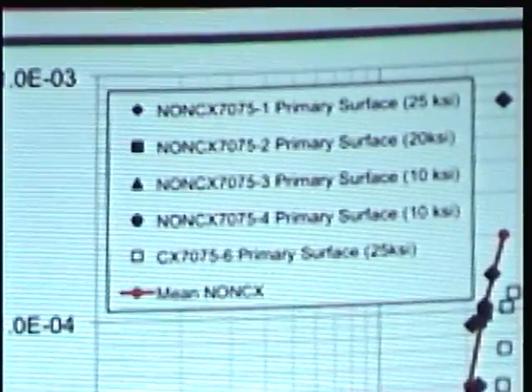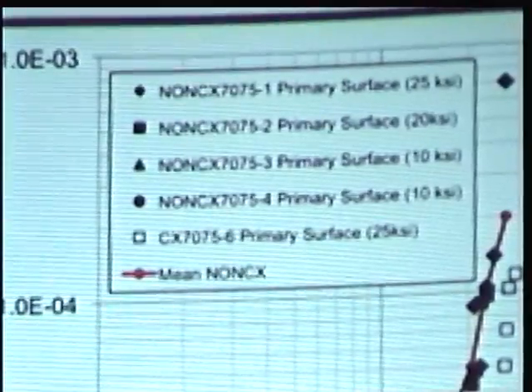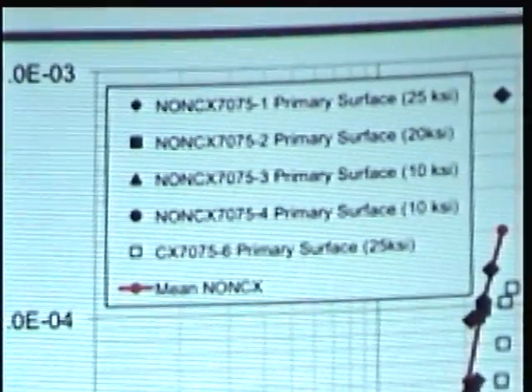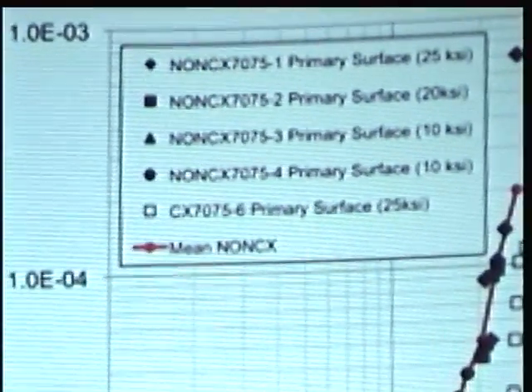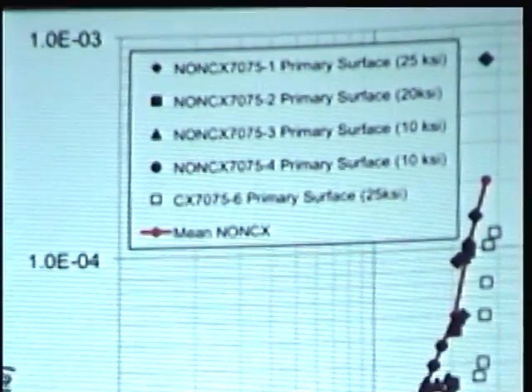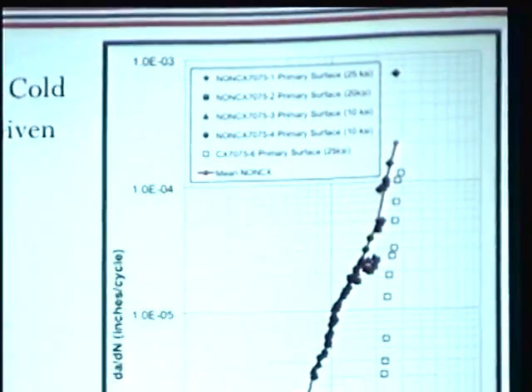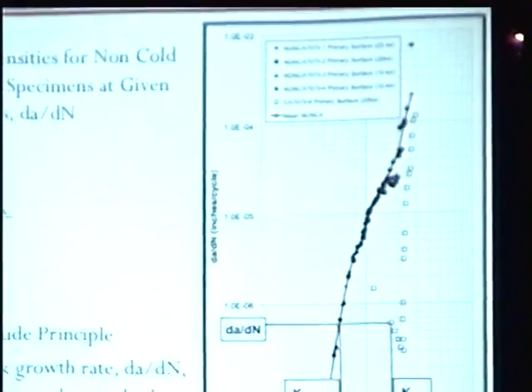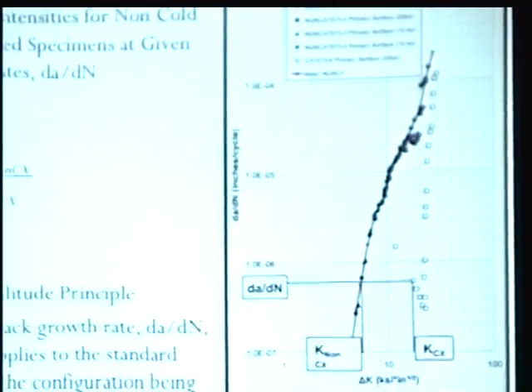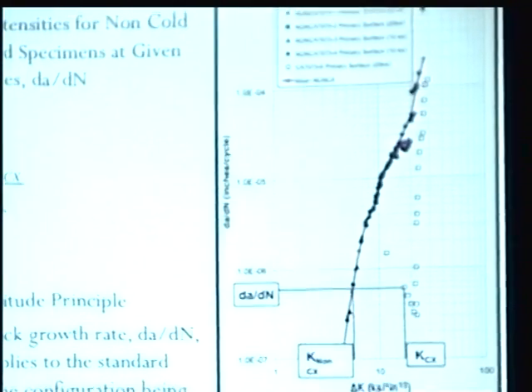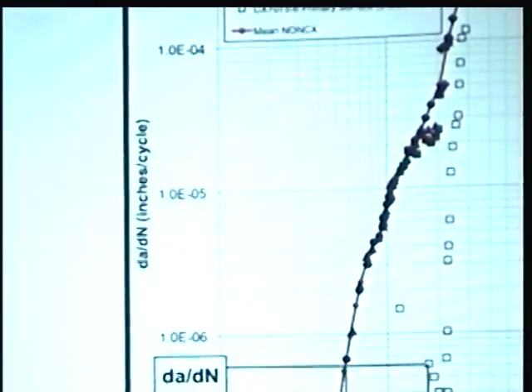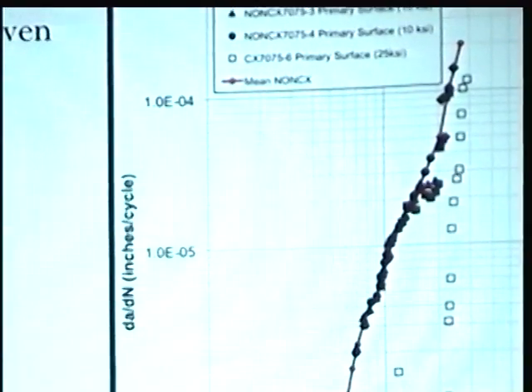But what if I process these? What about all my cold expanded specimens? How does that change? This is one example of one specimen. You see this shift, and that shift is an artifact of this process. You've actually shifted the data, and the only thing causing that difference is that actual process. That's the only thing different between these specimens, and that's an artifact of cold expansion.